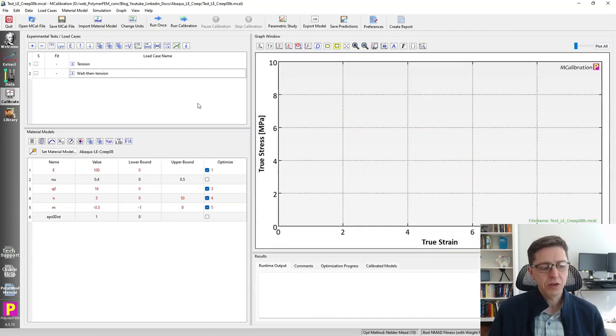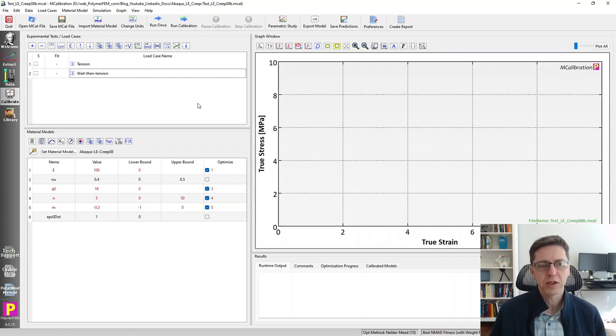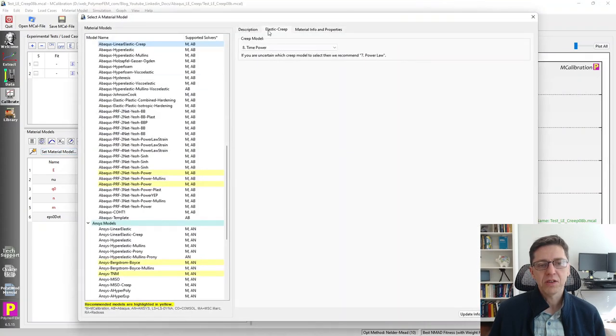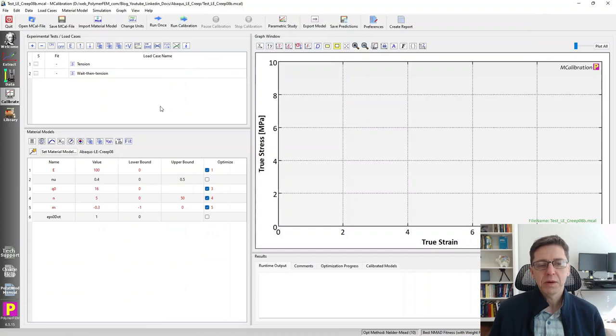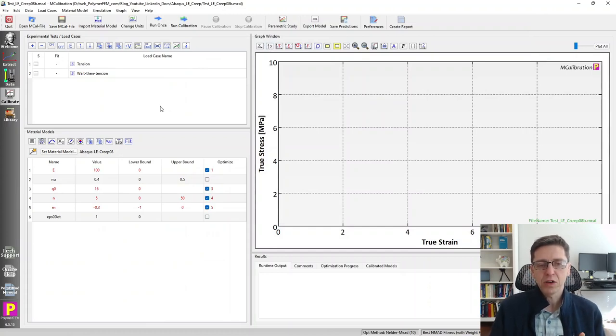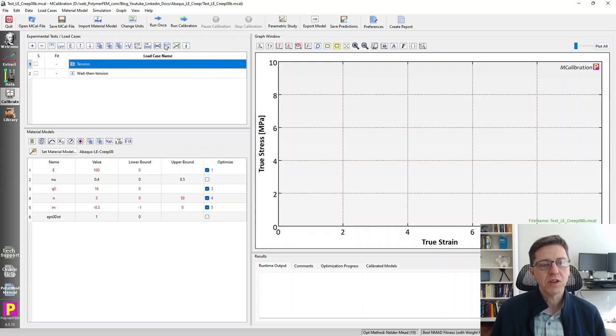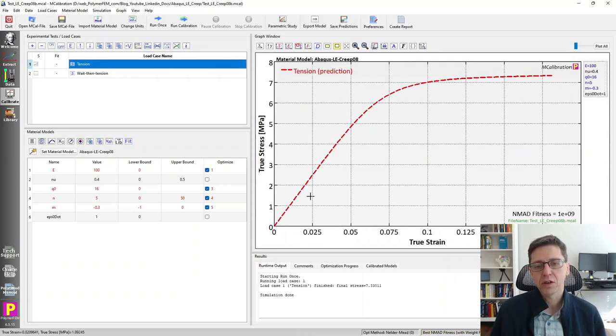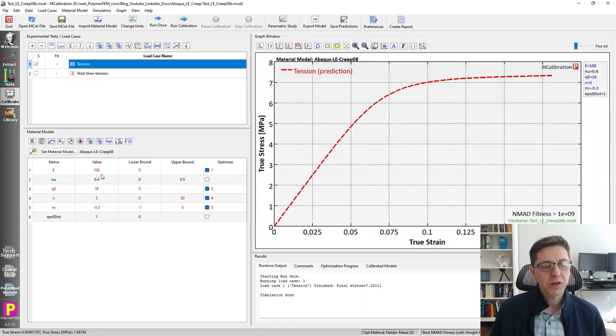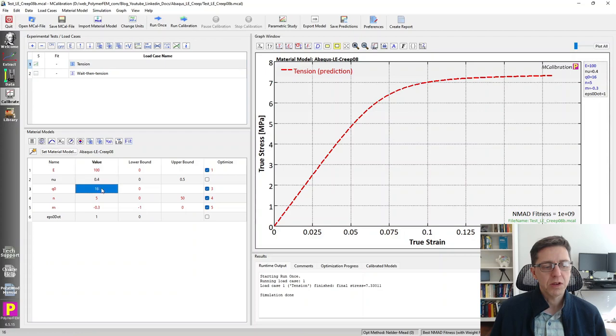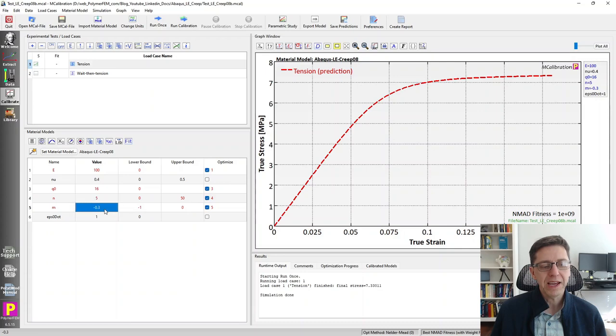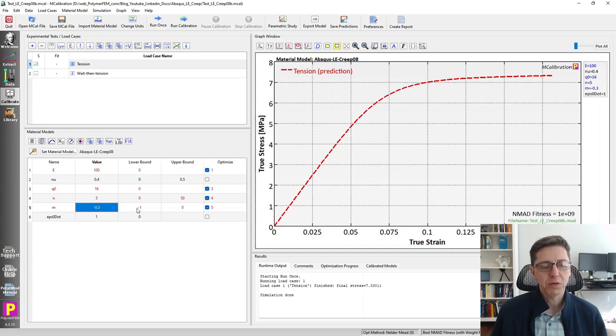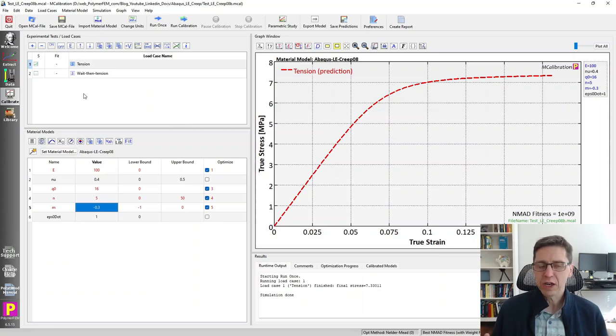Another model that people often use, which is really a bit unfortunate and of course difficult to use, is creep model number eight here. And this is the time-power model. So this is the model where the creep rate depends on the stress, but also on time. So basically saying the rate of creep depends on the time itself. And this can be a problem. So if I just do a tension test here, it's a virtual test that just goes like this. And that's fine and all, but let's look at the parameters. Young's modulus, this is the flow resistance, N is the stress exponent, and M is now the power exponent for time. So creep rate is proportional to time raised to the power of minus 0.3, and it has to be between minus one and zero.